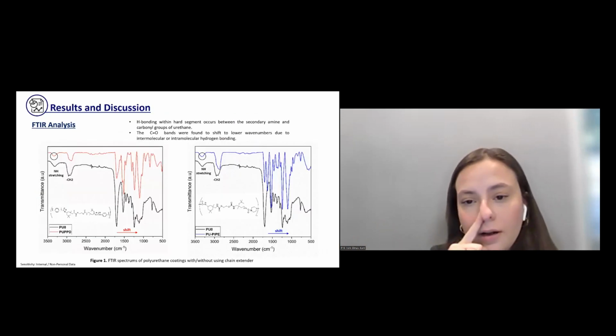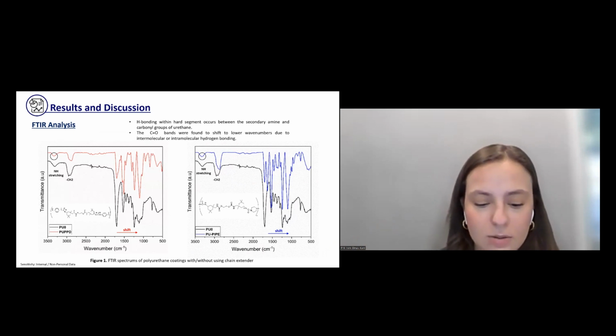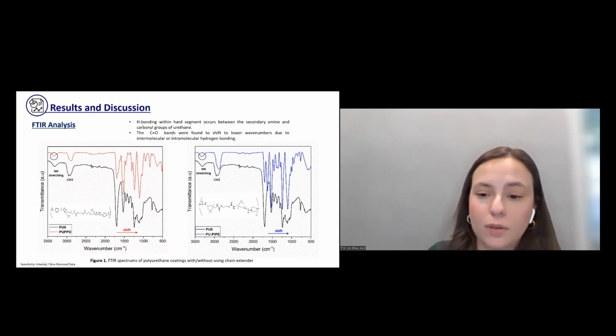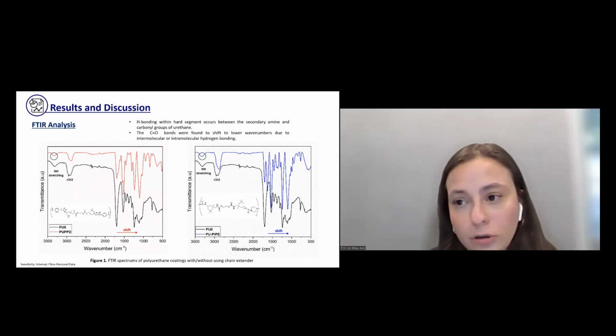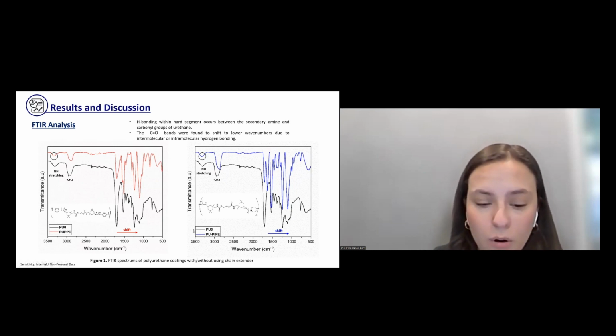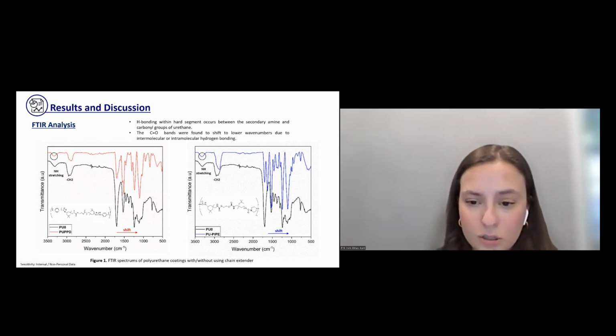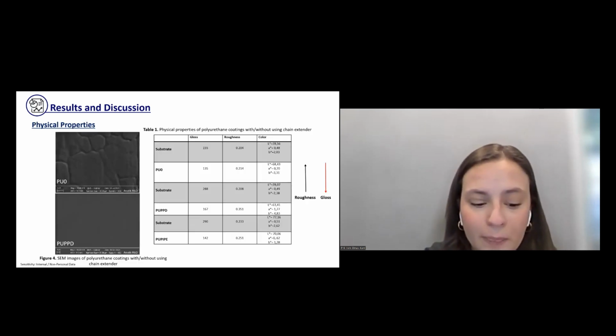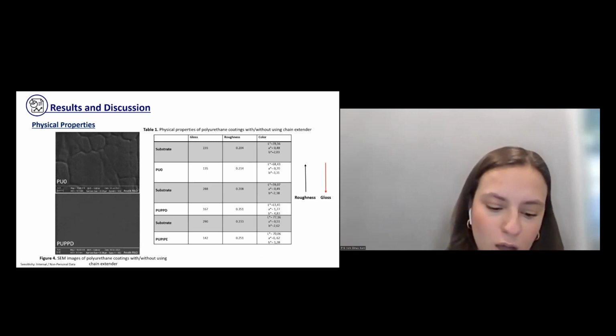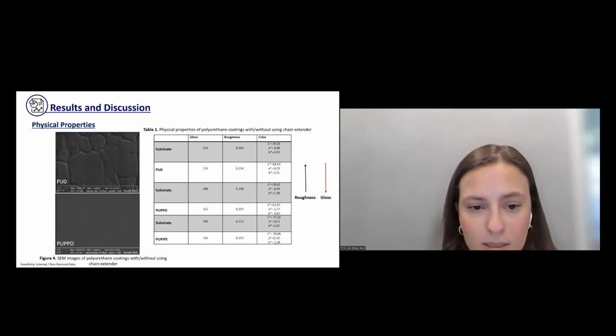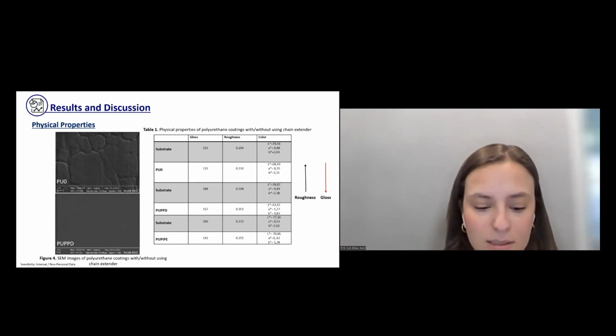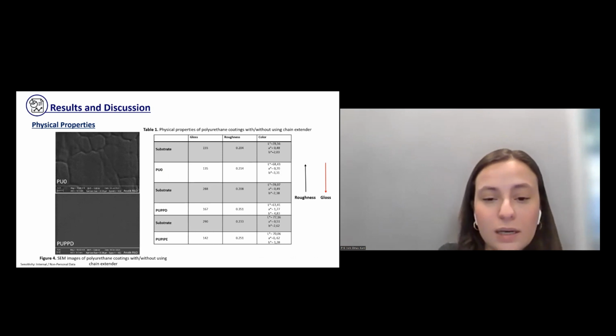When we look at the FTIR analysis, we can see the characteristic peaks, and the carbonyl bonds were found to shift to lower wave numbers due to the intermolecular or intramolecular hydrogen bonding. And our work on FTIR analysis and interpretation of peaks continues. In the SEM image, the surface of the diamine chain extended polyurethane coating was homogeneous and smooth, whereas the blank polyurethane coating had a wrinkled appearance. The piperazine sample has not yet been analyzed.